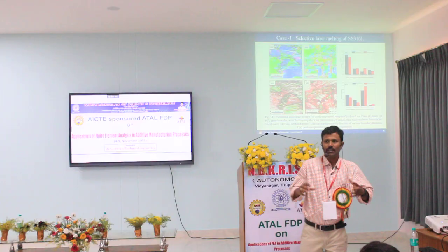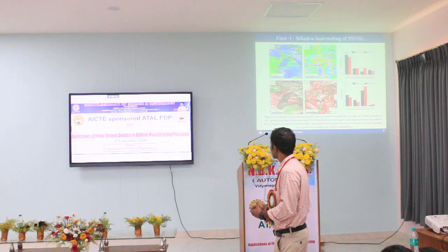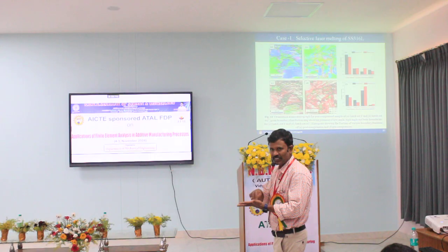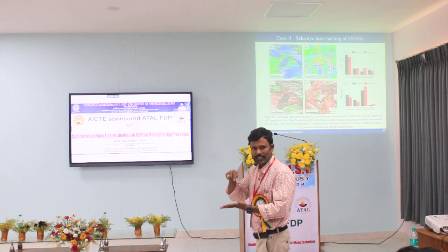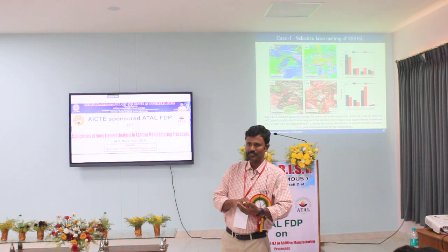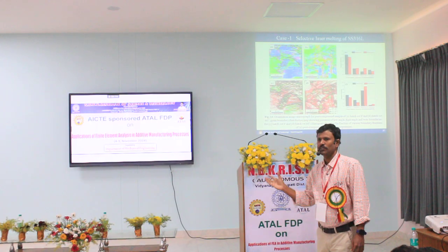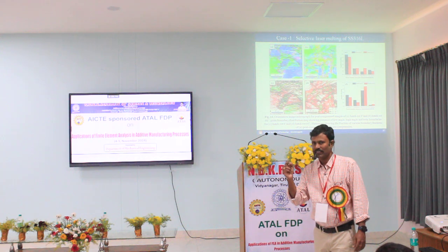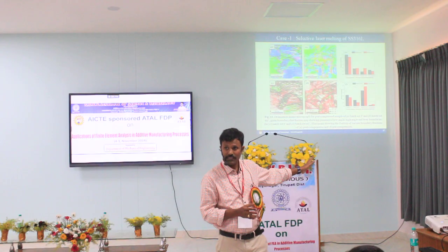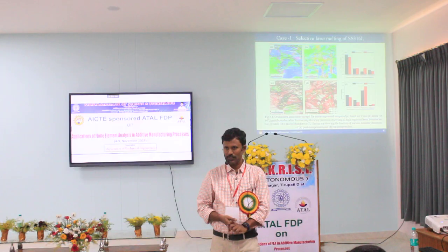Yeah. When you combine the information of whatever I have mentioned, you will see like this. You can see where strains are more, whether in that location misorientation angles are more, or dislocations are more, or low angle boundaries are more, or stacking faults are more. All the information in one nutshell you will get. This also you can use: which is the hard spot or which is the weaker section, where the damage can initiate. Yes, you can use it. This is a physically defect-free system I am saying. If porosity is there, that is a defect domain.